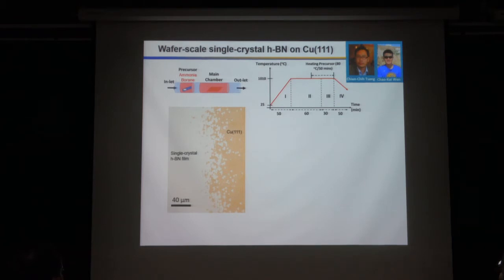But typically, high quality material of this kind can be obtained by exfoliation. So we try to use CVD to grow wafer-scale boron nitride. This is an example. We grow this material on copper 111. You can see this is a continuous film, this is an individual flake, and this is the transition region. We intentionally grew such a large gradient to show this effect. Actually, the growth rate is very fast, so you can directly cover one monolayer on a full wafer. But we use a technique to cover another substrate on top, so they form a very large gradient to show you the grain orientation.